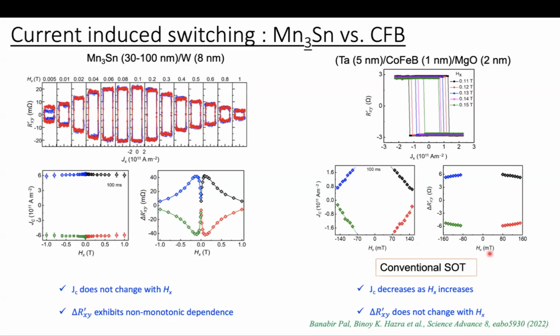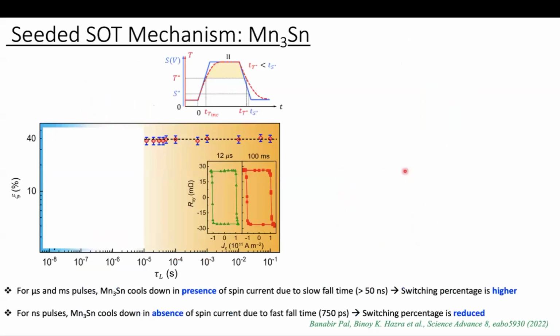So if you call this standard ferromagnet like CoFeB, where switching is because of the spin orbit torque, then the manganese three tin (Mn3Sn) switching is beyond spin orbit torque. So there is spin orbit torque, but there is not conventional spin orbit torque. To understand this switching mechanism in detail, we performed more experiments.